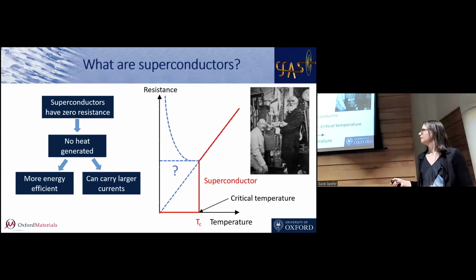And also, not maybe so obviously, it means that we can carry larger currents through the same amount of wire, the same cross-section of wire. The reason for that is that in a normal metal, if we start increasing the current through it, it starts generating heat. That heat increases the resistance of the metal, which generates more heat, and eventually it's going to melt. So there's some limit to how much current we can get through it without it melting. And superconductors do have a limit as well, but it's a lot higher.